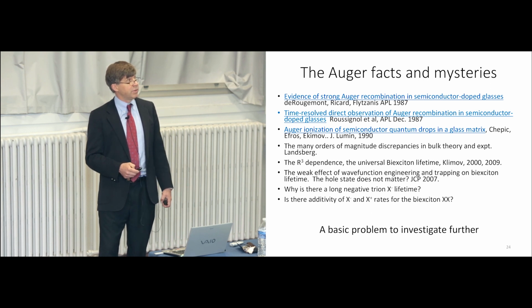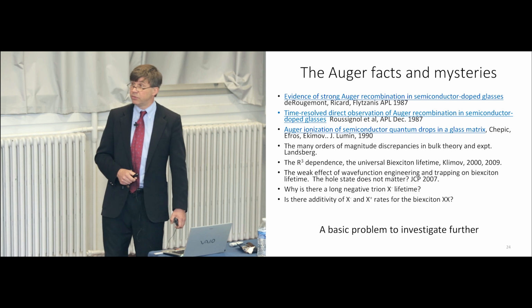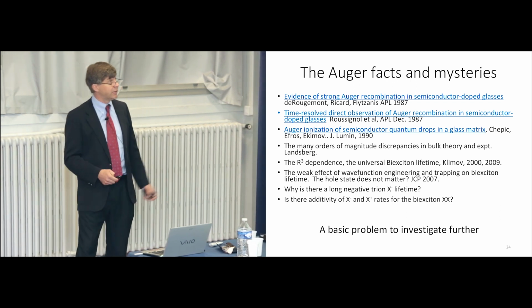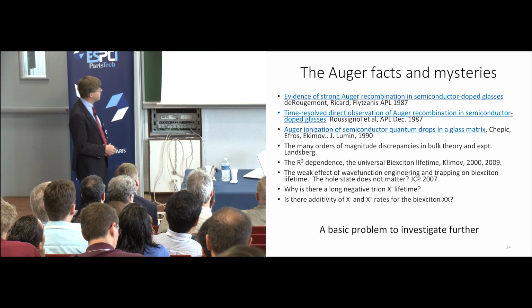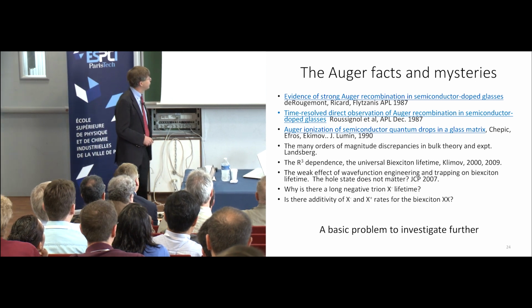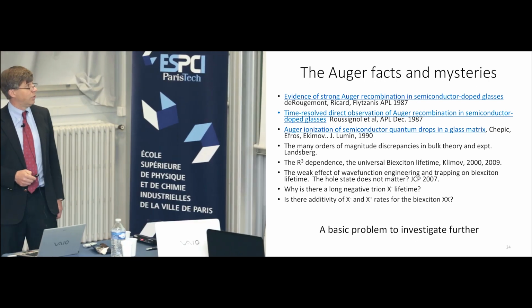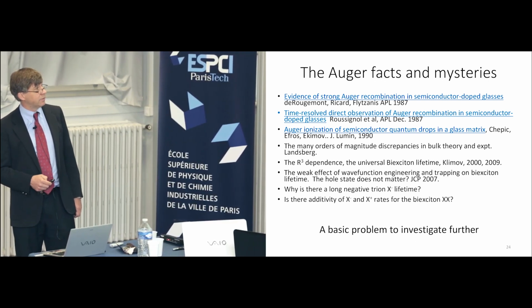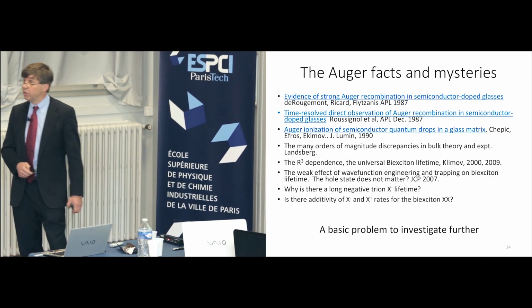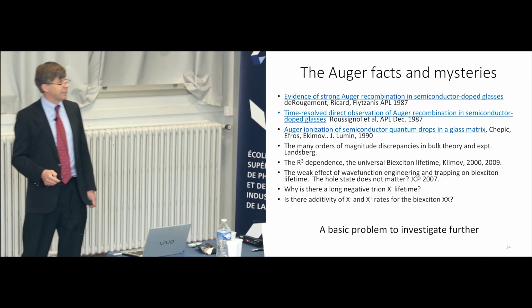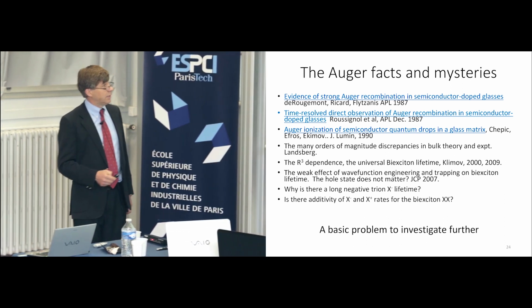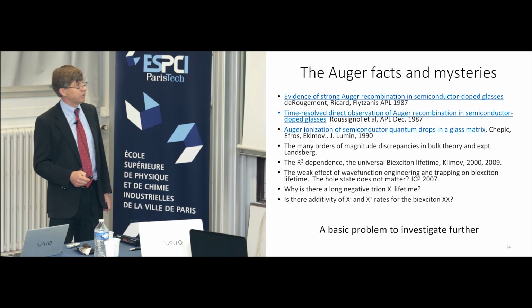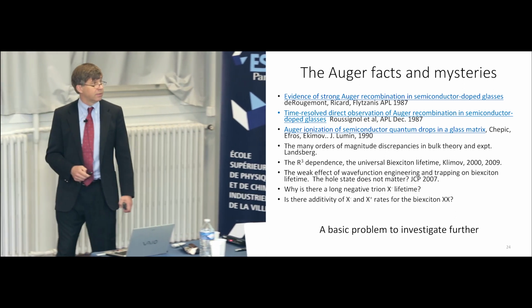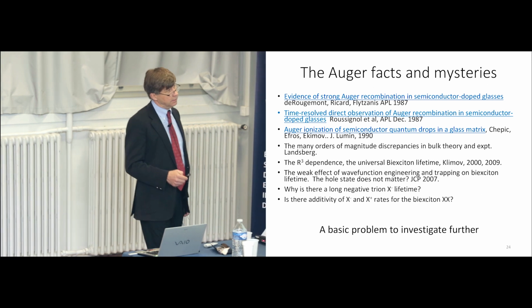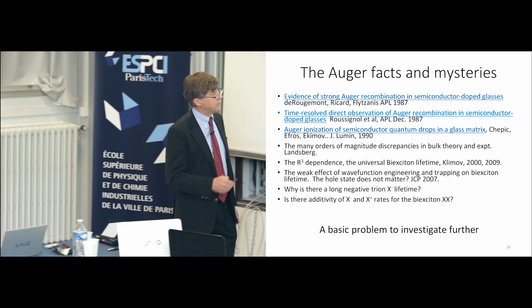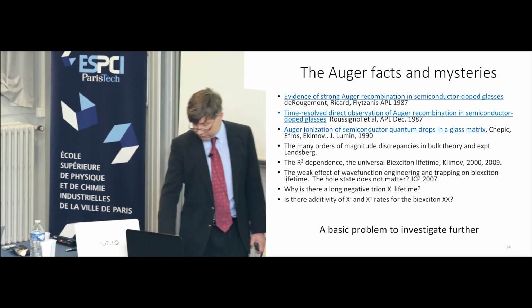We looked into this, and we tried to tweak the hole wave function and to see if that had an effect on the Auger. It should have, according to this matrix element, but it doesn't. That's in JCP 2007. We tried very hard to tweak that Auger biexciton lifetime, moving the hole wave function. It doesn't work. And then we have now results from many groups of very long-lived, high quantum yield trions, negative trions. And then we have this prediction in the single electron picture that there should be an additivity between the X minus, X plus rates for the biexciton. I think it still remains to be proven because the X plus is very hard to measure. So I think it's still a very interesting problem to investigate.